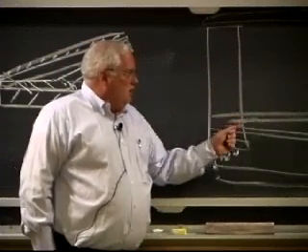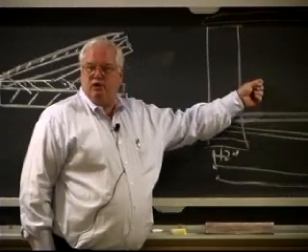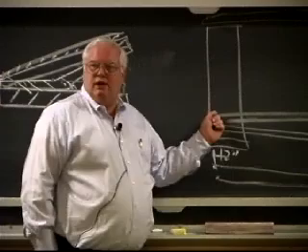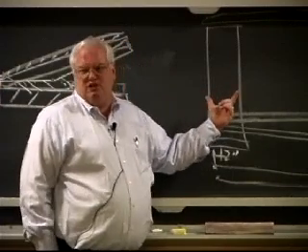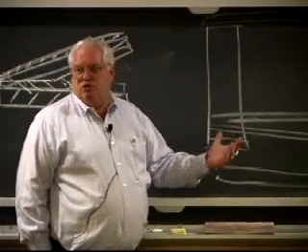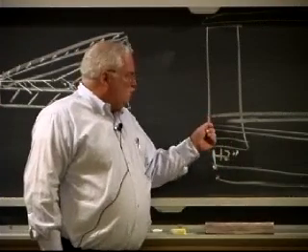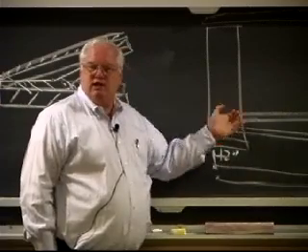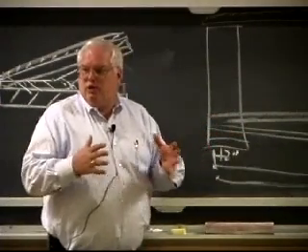So you have water or whatever cooling fluid going through this, and then you have a fluid on the other side, and that's your heat exchanger. Well, you don't want any gaps between the tube and the tube sheet, which is really a plate, right? It's a 12-inch thick plate. You don't want any gaps in there because you'll get corrosion. You get crevice corrosion. So they do all kinds of things. Sometimes they just weld to the top, and then they roll it as tight as they can to deform the tube against the tube sheet to keep any crevice from being there.